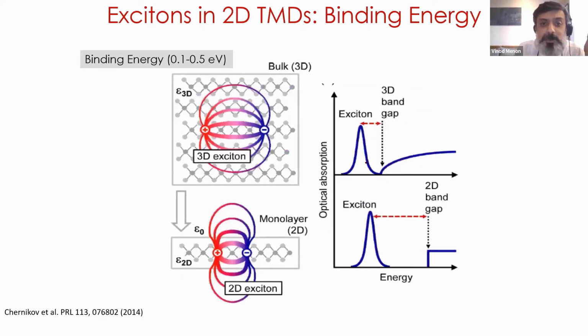If you look at their binding energy, if you take a semiconductor which is bulk in 3D and look at its properties, you will see that the exciton energy sits here, and then you have a quasi-particle band gap which starts somewhere here, and this is your binding energy. But when you go to the monolayer limit, you have a very weak screening here and here, in other words, there are no carriers there. The screening is usually what affects your overall Coulomb attraction between the electron and the hole, which is now much more tightly bound, and hence your exciton is much farther away in energy from the band gap, and it's very tightly bound because of the two-dimensional nature of these excitons.